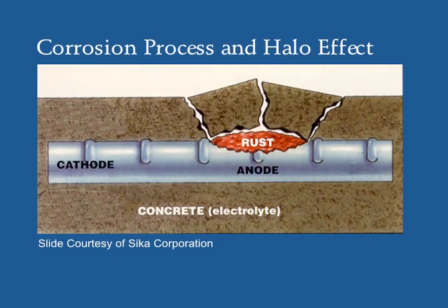After a while, the maintenance forces will come along and finally replace this deteriorated concrete. They'll replace it with chloride-free concrete in this patch, and then subsequently, this part of the system, previously the cathode, will become the anode, now having greater chloride concentrations than its adjacent steel. And now the corrosion process will be initiated at this location. Thus, you see how the halo effect occurs in the field, a continuous growing of this damage process.